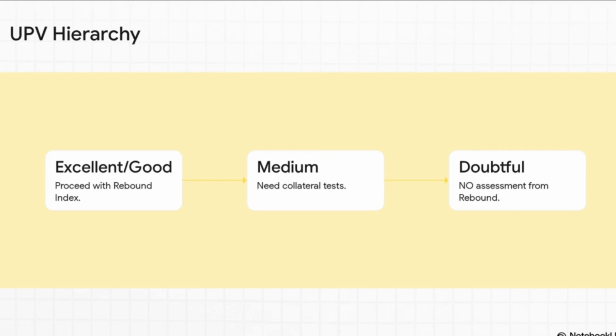The UPV test actually dictates whether you are even allowed to trust your rebound hammer data. It's basically a hierarchy. First, if you scan the concrete with UPV and the quality is assessed as excellent or good, you're clear to proceed. You can totally trust the rebound index to estimate the compressive strength. Second, if the UPV results are only medium, you can't rely solely on the hammer. You have to bring in collateral tests, like checking site cubes or doing limited core drilling to verify the numbers. And third, if the UPV test shows doubtful quality, meaning sound is moving sluggishly through a fractured interior, you must make absolutely no assessment of compressive strength from the rebound index. The standard strictly forbids it because the surface bounce is essentially lying about the internal decay.